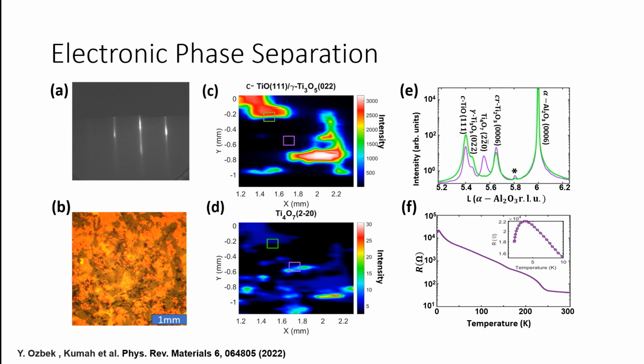For a lot of the other materials, the materials are single phase, but if you're close to a boundary, you can actually nucleate the different phases in the same material. And if you measure the transport properties, you can see all these different transitions which correspond to the different phases present in the system. But what's interesting here, and what's motivating some of the work we're doing now, is that because you can have a coexistence of the insulating phases and the metallic and superconducting phases, then you can make something like a Josephson junction. You can make a qubit if you can actually make layers of these systems in well-defined ways.